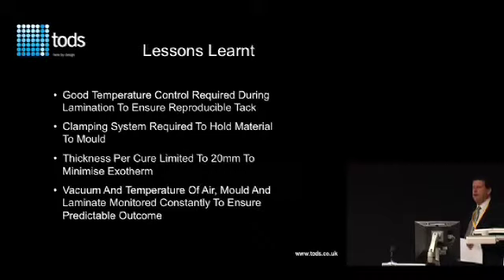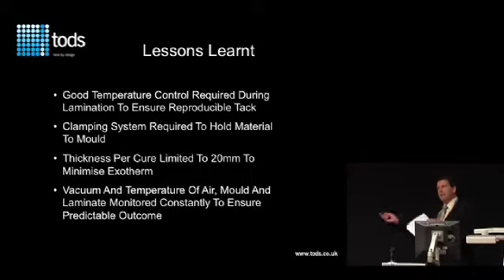The tack is very dependent on temperature, so we effectively air condition the room. If the temperature is too hot, you've got too much tack and you can't easily move the material. If it's too cold, you've got no tack at all. You need some sort of clamping system to hold the material on the top of the mould. If you don't do that and it slumps, it's impossible to get it back into its original position.